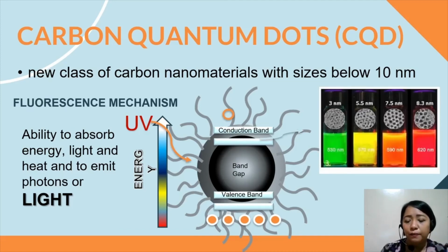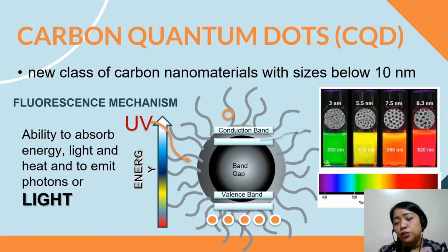So what's unique about this is the color or the fluorescence depends on the size of the quantum dot. So for example, if your quantum dot is in the range of 3 nanometers in size, it emits a green fluorescence, and as it grows, the size gets bigger. For example, in the range of 8.3 nanometers, it will emit a red colored fluorescence.